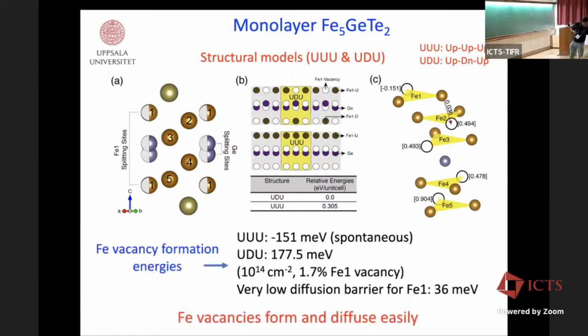Also, what we have seen is that if you calculate the iron vacancy formation energies, in the UUU structure, when all the iron atoms are in the upper layer, you have a spontaneous formation of iron vacancy. That means it is not so stable. So some of the iron atoms try to go away from there.